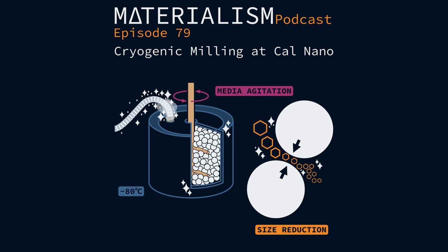Oh, yeah, absolutely. And it actually can help you create some really unique material properties and phases that would be difficult to get otherwise. For instance, you can get a lot of amorphous phases just because of the amount of destruction that you do to the crystal structures, and even a lot of metastable phases that would be difficult to form otherwise. And a lot of that happens because you're doing all this cold working, and then you're getting these really small quantities of material, right, these nanograins, right next to one another in a damaged lattice. Yeah. All of a sudden, diffusion and other sorts of things that would be, you know, much more spontaneous at a higher temperature end up becoming possible.